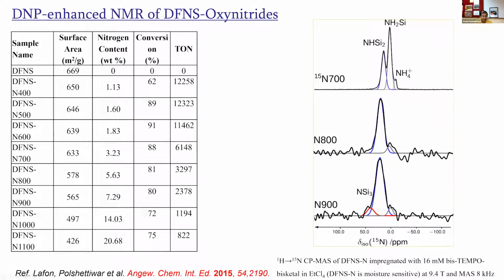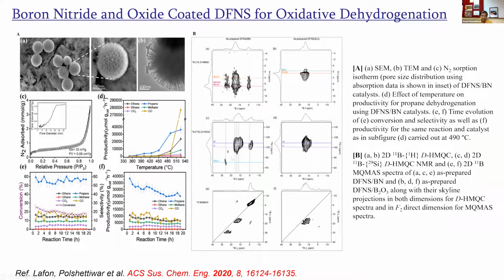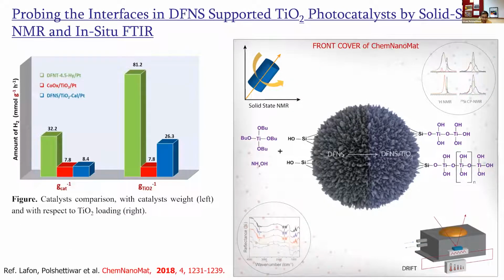Then we also recently showed that boron nitride and oxide-coated DFNS can act as a very good oxidative dehydrogenation catalyst, and we used 2D NMR to really understand what the real catalytic site is in these catalysts. In another material, the semiconducting-based photocatalyst, we used DNP NMR as well as in situ IR study to understand how the surface of the silica is reacting with the TiO2 precursor and how the TiO2 is really getting coated.